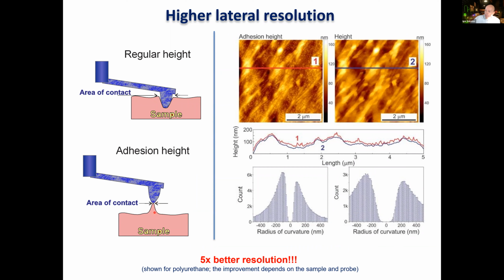It would be very easy to check, because if you have that probe, you literally tap exactly the same point again and again, and you'll see if it's really repeatable, because there is a lot of stochasticity here. Even if you do exactly the same thing, it's uncontrollable, or I would say quantum, but at least definitely stochastic. We are unlikely to get exactly the same measurements. I would say we definitely will see something, but it's better to check than to hypothesize what exactly we would see. And definitely it will be much sharper resolution than a regular direct contact.